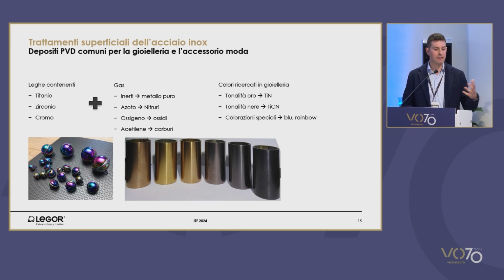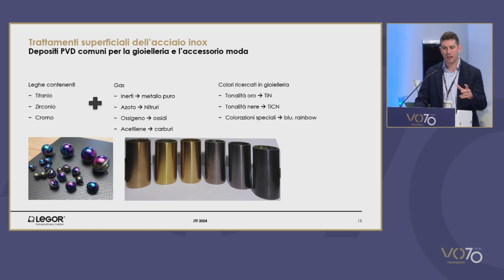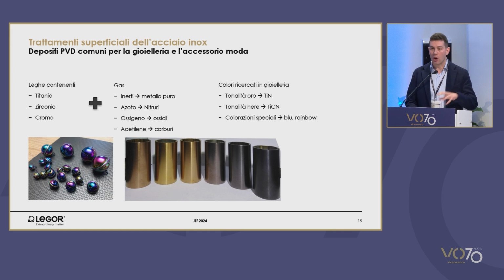Coating by means of PVD includes titanium, zirconium, and chromium, which interacting with inert gas can create the pure metal, or there could be oxides and the carbides of the above-mentioned materials generated. The colors that are usually resorted to in the jewelry and fashion industries are the ones that simulate gold, and those are obtained by means of deposition of titanium nitrides that look more like 24 karat gold.